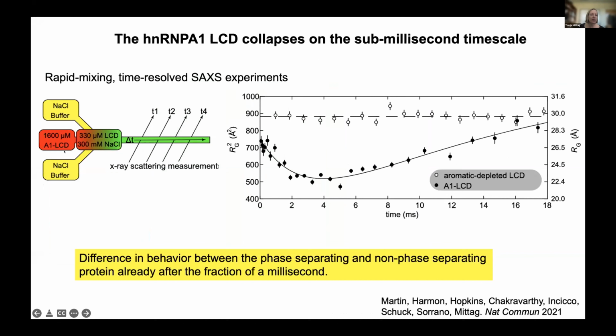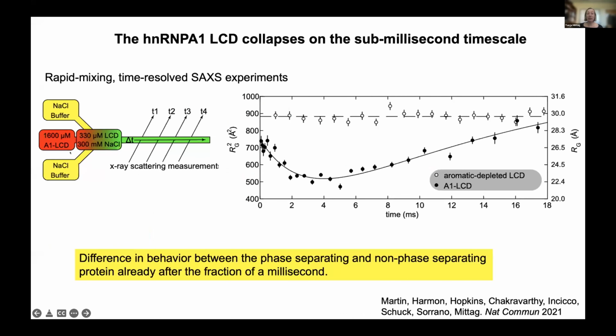He started off with the HNRNPA1 low complexity domain in a solution without excess salt, where it's highly soluble, and then jumped through rapid mixing to a condition where he was in the two-phase regime, and then was able to follow how quickly the solution nucleated. And he followed this by small angle X-ray scattering, so that you can see small changes in the dimensions of the protein, as early as 60 microseconds after mixing.